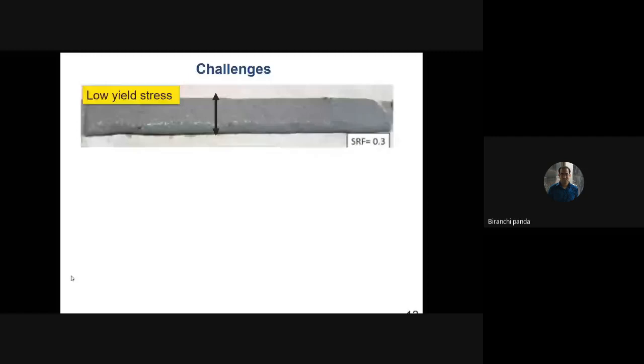It should not be more, it should not be less. But if the material design is not proper, once you deposit, the material will simply flow away. So it happens because of the low yield stress of the material. Now I'm connecting some engineering technical term to this process. So when the material is going to have low yield stress, once it is extruded out, it can simply flow away. But definitely we do not need this kind of property in our printing process.